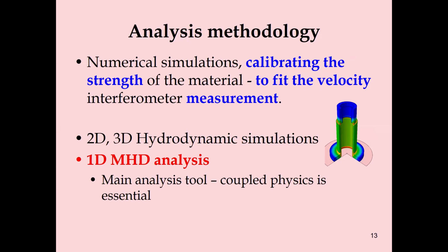So how are we analyzing the strength from these materials? We're going to look at the velocimetry signals in a minute, but we're using numerical simulations and we're calibrating the strength to fit the velocity measurements we're getting in the experiments. We're going to look at the sensitivity of this in a couple of slides. So we started off with 2D and 3D hydrodynamic simulations just to examine the behavior of the entire setup. But eventually, to get the right accuracy when we're looking at the strength measurements, we came to realize we need to take into account the coupled behavior of the magnetic field and the hydrodynamic behavior of the cylinder. So the main tool we're using is a 1D MHD hydrocode to analyze the behavior.